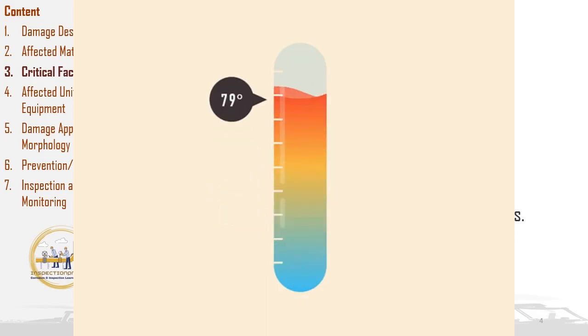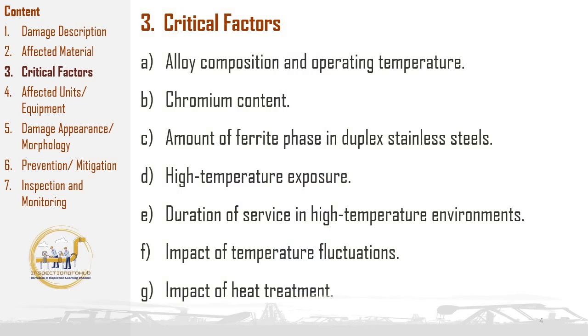Temperature fluctuations can significantly affect the toughness of materials, particularly when they experience rapid cooling or heating during plant shutdowns, startups, or upset conditions. While the impact on toughness may not be pronounced at the steady operating temperature, sudden drops in temperature can cause materials to become brittle, especially if they are already susceptible to embrittlement due to prior high-temperature exposure. This is because the ductile to brittle transition temperature can shift, making the material more prone to fracture under stress at lower temperatures. Hence, managing temperature variations is critical to maintaining material integrity and preventing unexpected failures during operational transitions or abnormal conditions.